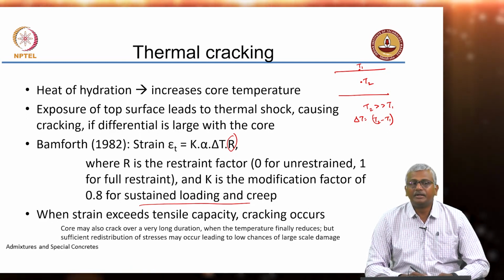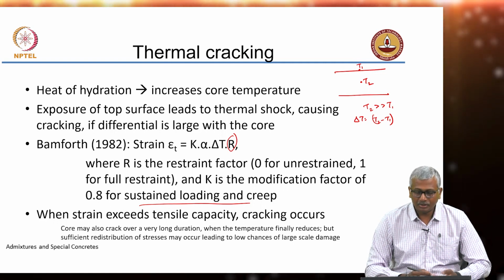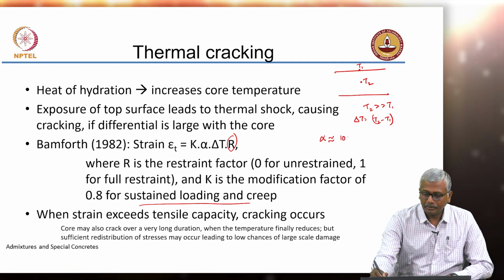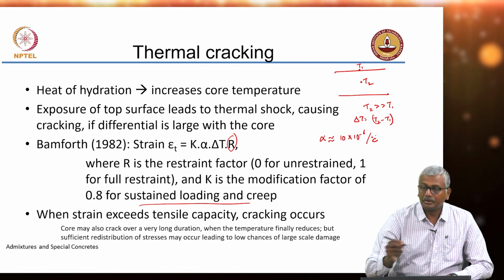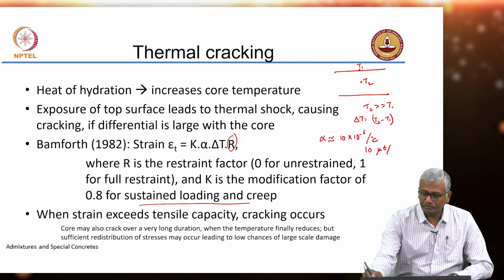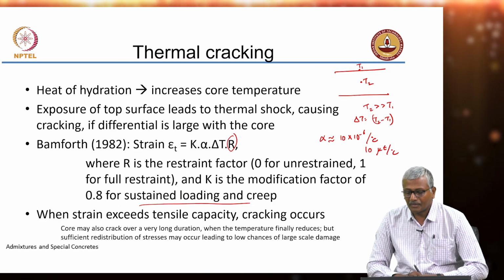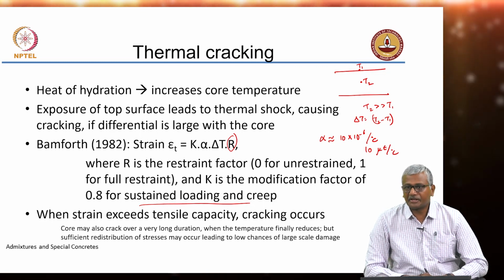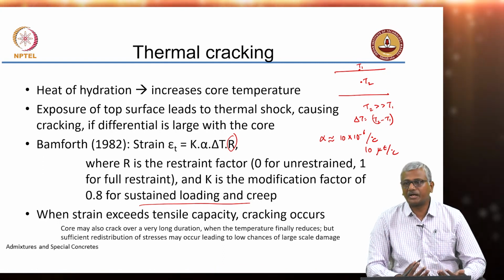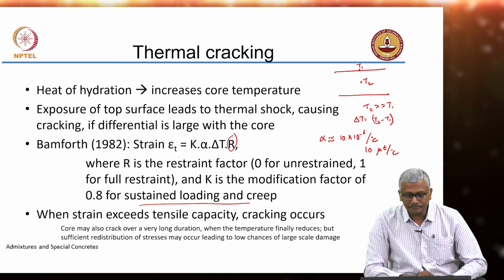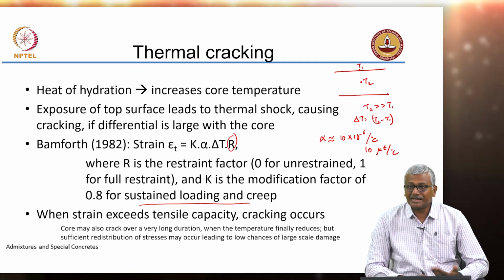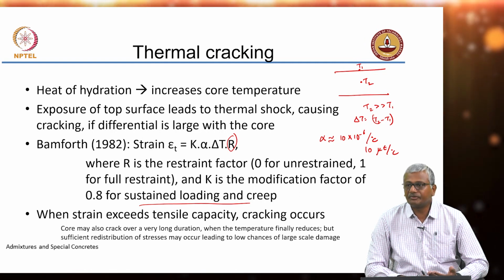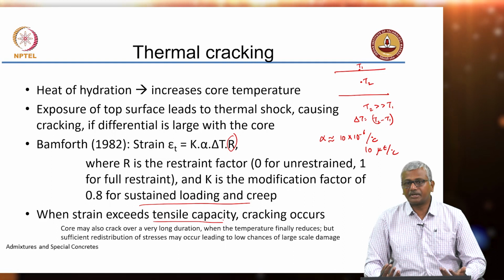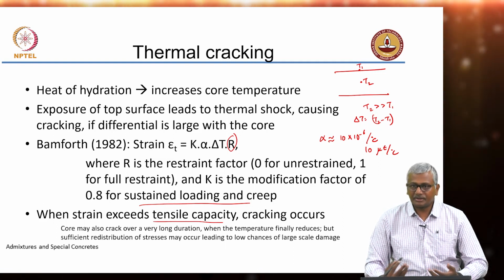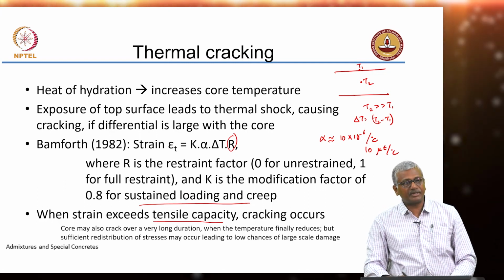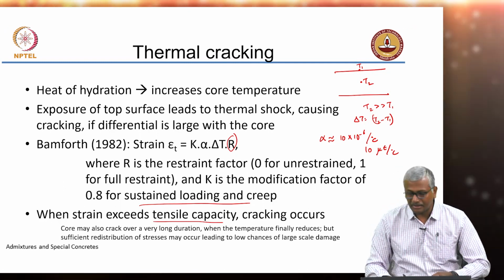Alpha is the coefficient of thermal expansion of the concrete. How much is alpha? 10 into 10 power minus 6 per degree Celsius, or 10 microstrain per degree Celsius. Okay. That is the coefficient of thermal expansion of concrete. Steel also has a similar coefficient of thermal expansion. Okay. So this tensile strain that is created because of thermal differential, when it exceeds tensile capacity, cracking occurs, right? When the tensile strain capacity is exceeded by the thermal strain that is created because of temperature differential, you will have cracking in the system.